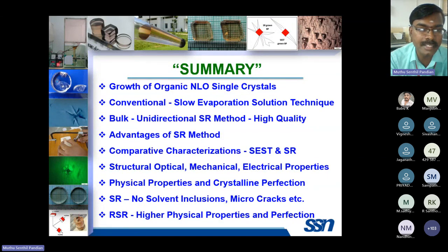This can be done in the RSR method. In the case of the RSR method, what we have done is we made several holes and several slots. We completely rotate the experimental setup of this RSR method with the seed crystal, with the solution, with the glass sample. So one can easily minimize the impurity segregation in the RSR method grown crystal.